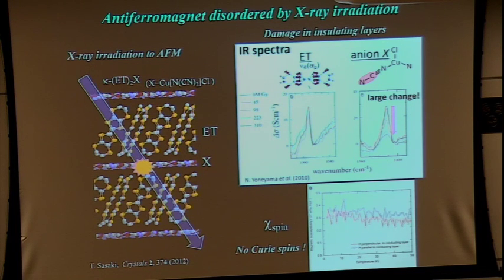However, the spin susceptibility does not show any Curie term. If the sample contained conventional defects, the magnetic susceptibility should show Curie-like behavior at low temperatures. However, there is no Curie-like behavior. So this means no orphan spins are there, no free spins. All of the spins are strongly interacting, and disordered.